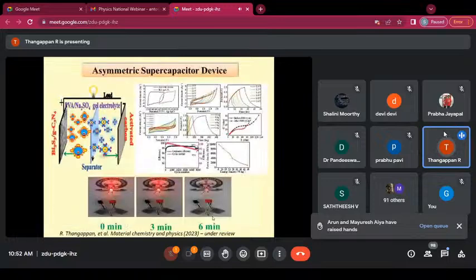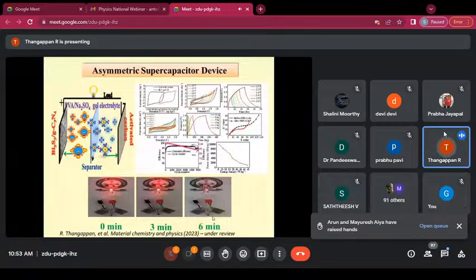We also fabricated an asymmetric supercapacitor device for the composite material. Carbon acts as the negative electrode, and the positive electrode was designed with the bismuth sulfide and graphitic carbon nanocomposite on the substrate, in a two-electrode system with a solid-state electrolyte, PVA plus Na2SO4. We performed electrochemical studies and fabricated a pouch-type cell, and we also glowed an LED. With 1 minute, 60 seconds, of charging, we achieved 6 minutes of LED light discharging, with a 1 centimeter by 1 centimeter coated electrode material for the supercapacitor application.